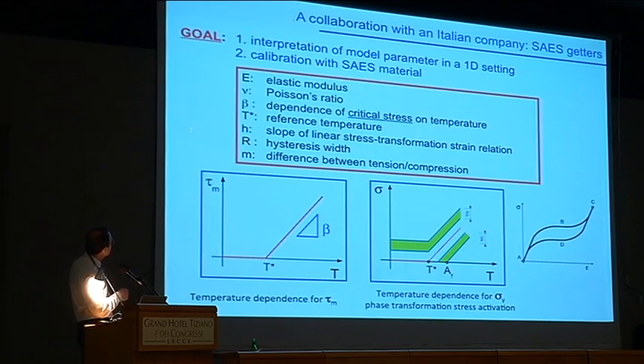So let me point out again the material parameters of the model, in which I was kind of fast. You have some elastic quantities, the standard ones, elastic modulus and Poisson ratio. You have beta and T star, which I already introduced. And then you have 3 other quantities. So you have a total of seven material parameters you have to choose to make this model run. And this is a very limited number of parameters. So beta and T star, T star, as I told you, was appearing in the definition of the T-M function, is the temperature below which basically you have the shape memory effect. Above T star, you start to see the superelastic effect.